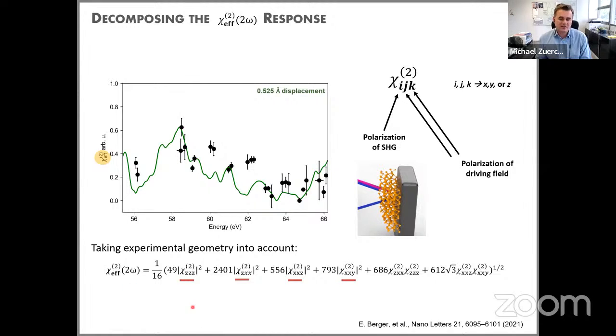The other thing you have to do is, if you orient it so that you get a projection, you have to think about how you can disentangle it. But the good news is that once you know what the projection is, even though you measure an effective Chi2, you can still learn something about which components you are most sensitive to, and get an idea of how these different components contribute to the observed spectrum.